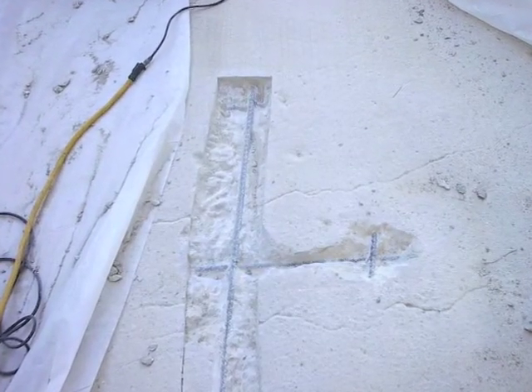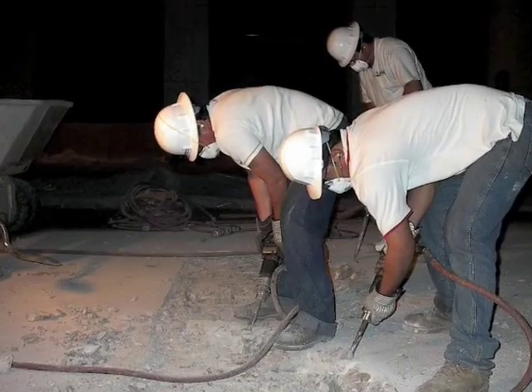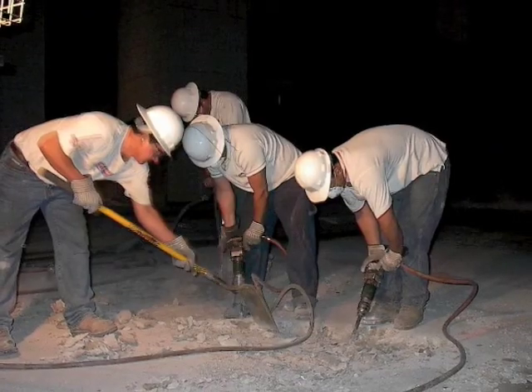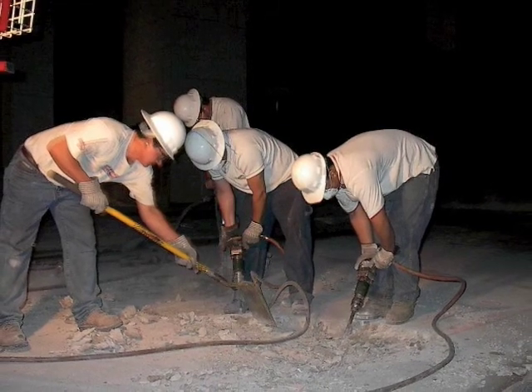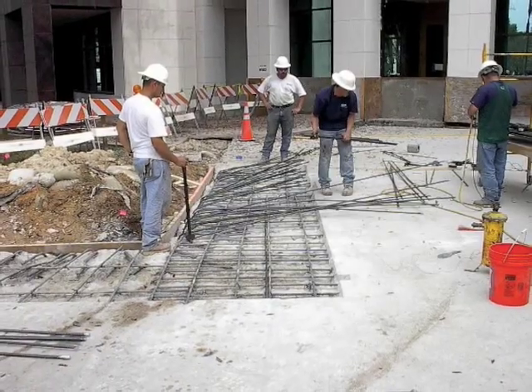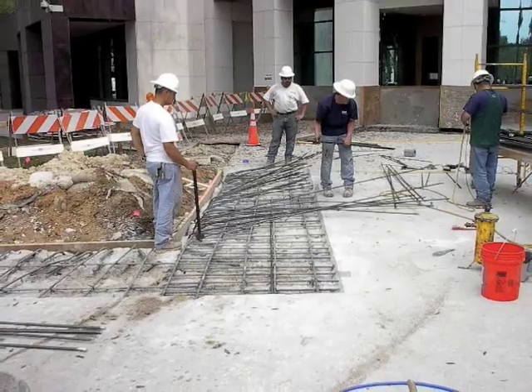The exposed deck revealed the concrete cracks and spalls, so prior to starting the strengthening process, we needed to perform extensive concrete repairs above and below the deck. In this particular area, we're adding rebar for strengthening purposes.